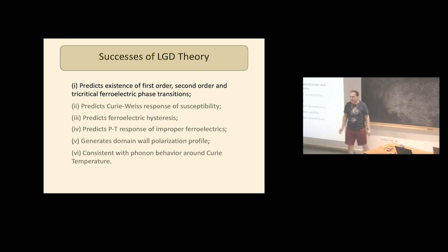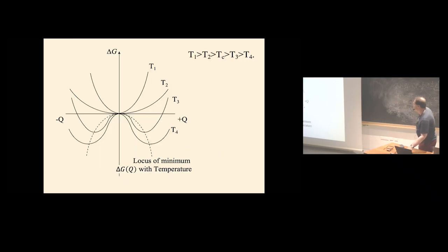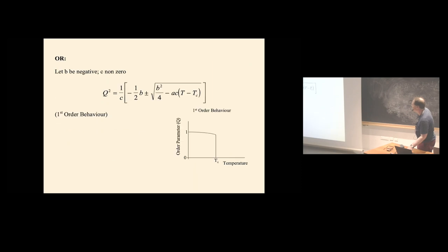Okay. So we have an explicit expression for the susceptibility of the polarization in this ferroelectric to applied electric field. Above Tc, P is equal to 0, and so this just comes out as 1 over A(T minus Tc). That is the Curie-Weiss law.